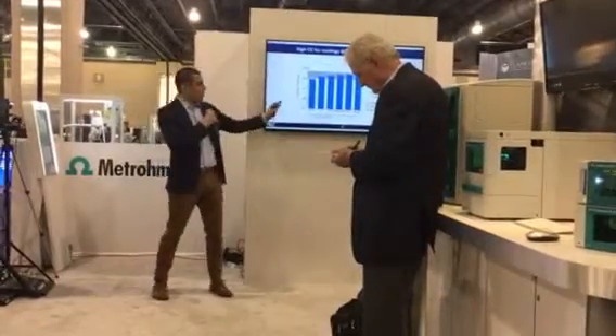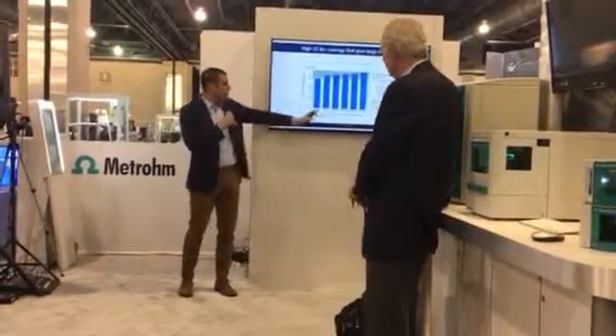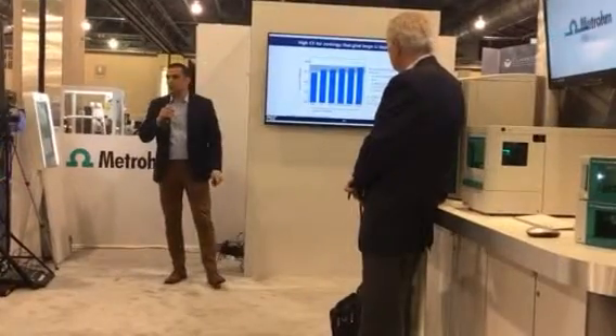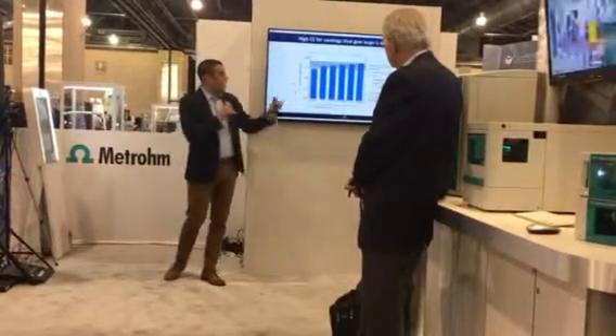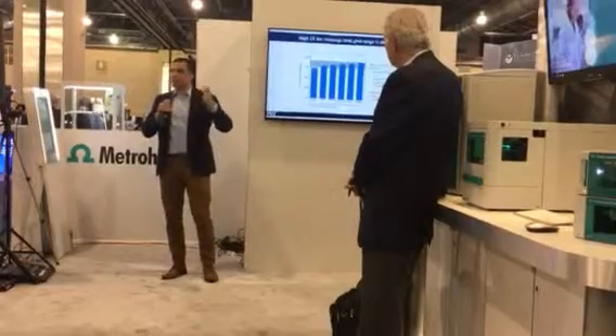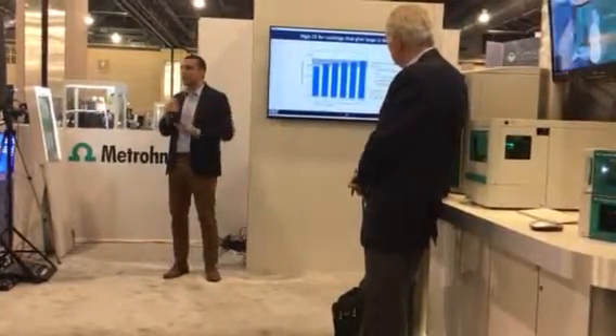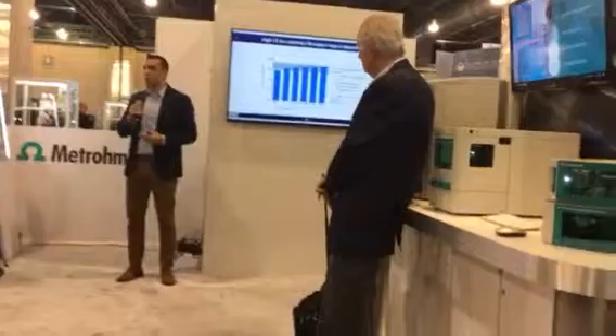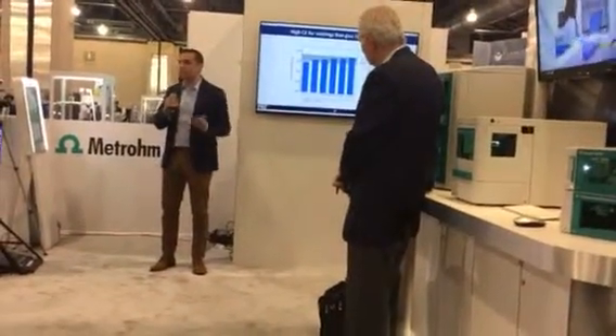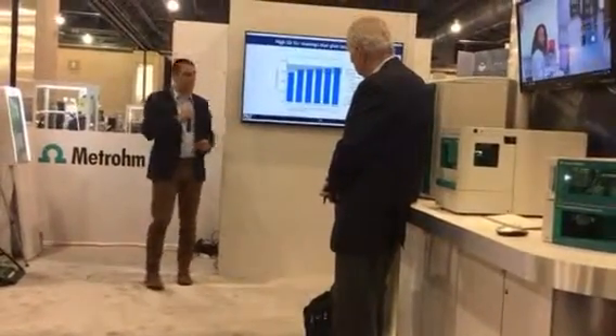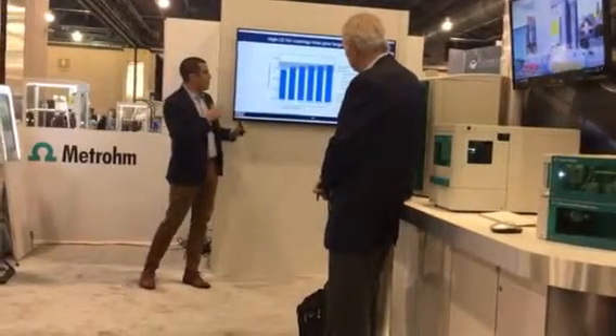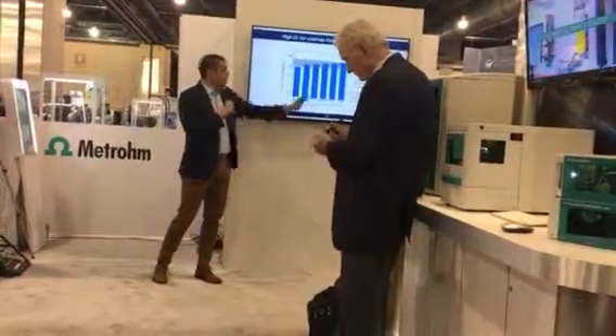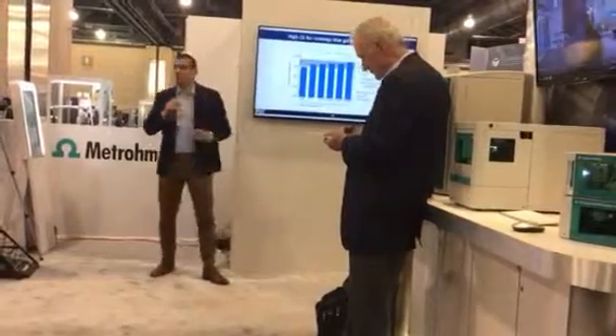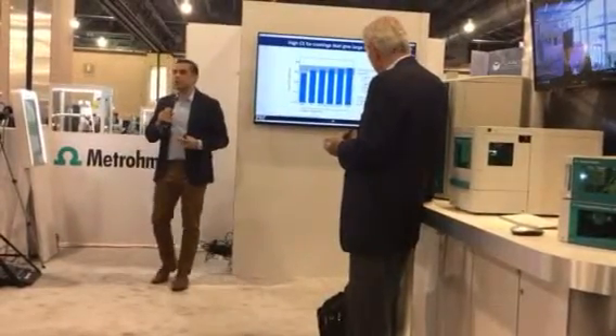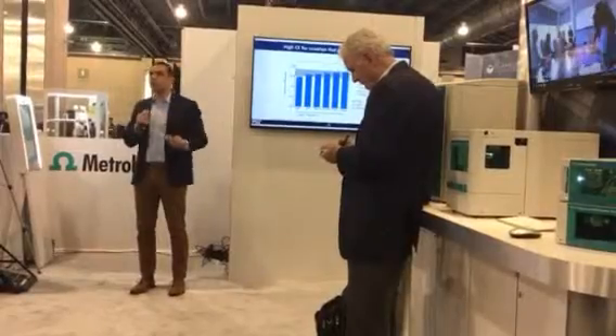Using this understanding, we're able to walk our efficiency up from left to right. So this is that first polymer I showed you here on the right at about 98% efficiency. So that's just every cycle you lose about 2% of the lithium, which is certainly not good enough to put in your cell phone or your car. Your battery would die in just 50 cycles, so 2 months of charging and discharging your cell phone. But we're able to go up, using our understanding that we developed here, to this new polymer that's over 99% efficient. And so as we continue to develop this understanding, continue to make new materials, we'll be able to improve this and hopefully enable this technology very soon.